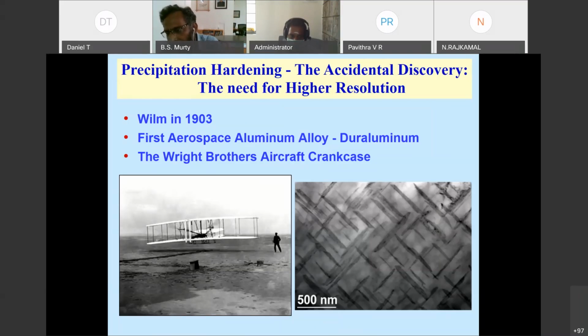But what is the reason for this particular aluminum alloy to become strong? What is happening during this aging process? Nobody knew at that time in 1903 when this was discovered. And people had to wait almost about 30 years for the evolution of a new microscope called the transmission electron microscope. And what you see, a microstructure on this slide, is taken from one such aluminum alloy, where the microstructure shows extremely fine precipitates, which are of the order of a few nanometers in thickness.